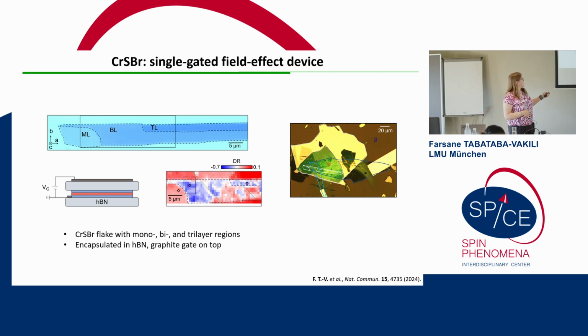And here is an image of the low temperature differential reflectance, which gives a measure of the absorption. And here blue color indicates regions of strong excitonic resonance, and the diamonds are the regions on the sample where we performed our measurements.